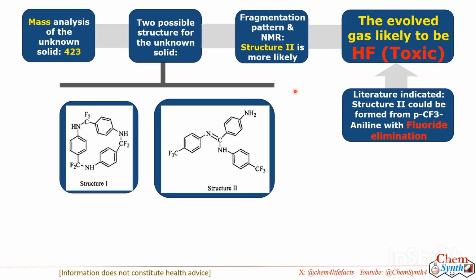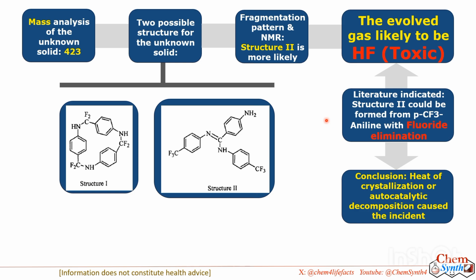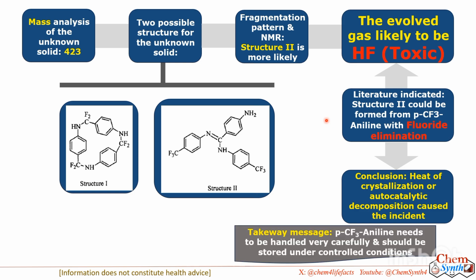This evolution of HF is supported by one literature also, where they mentioned that the structure 2 compound can be synthesized from this para-CF3 aniline molecule with the elimination of fluoride. So overall, from this observation, they concluded that heat of crystallization or any autocatalytic decomposition of the material caused the incident.